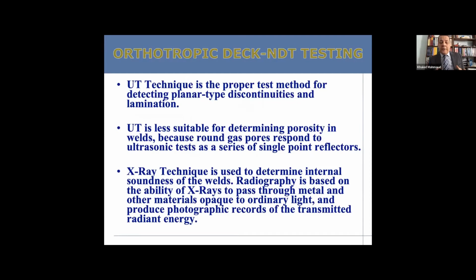Another thing that ought to be used is not only the UT techniques, but also X-ray. The UT, the ultrasonic testing technique, is proper for planar kinds of discontinuity, but the UT is less suitable in detecting porosity in the weld. That's why X-ray is a lot better technology to detect the porosity in the weld that can cause fatigue and cracks.